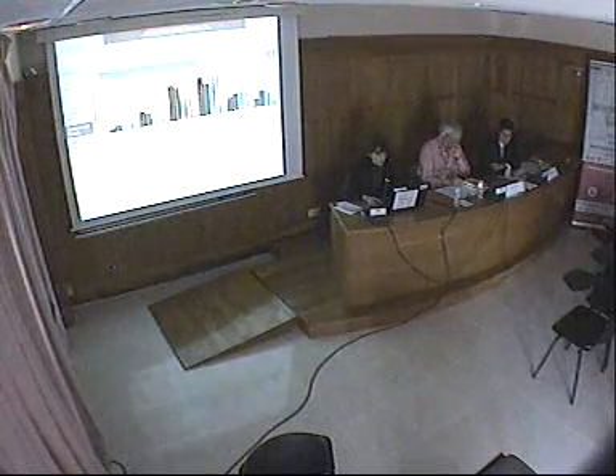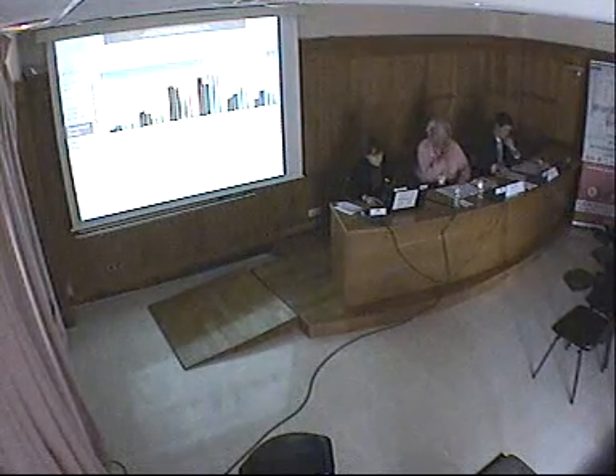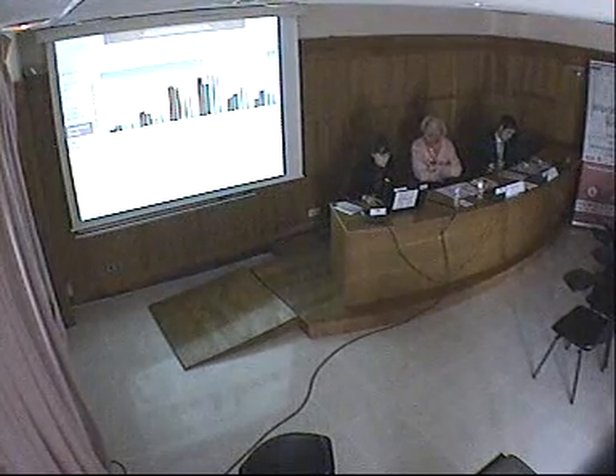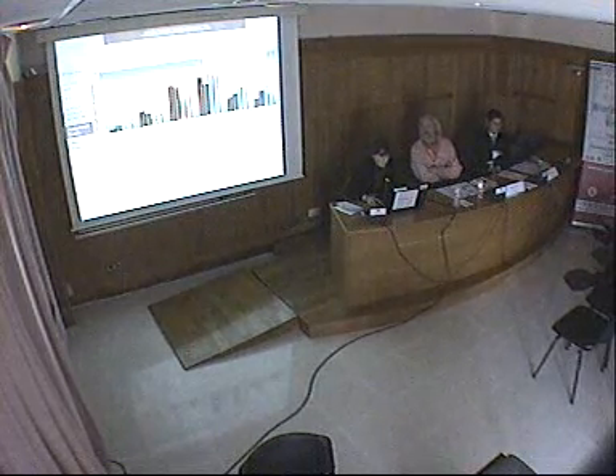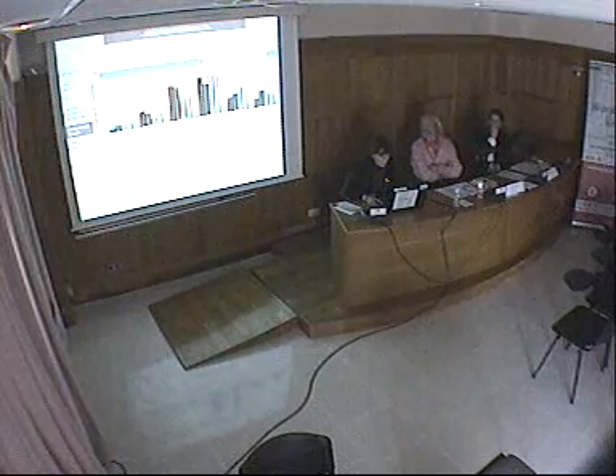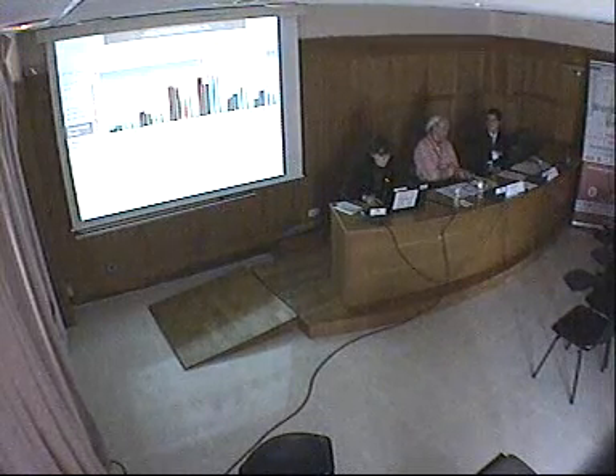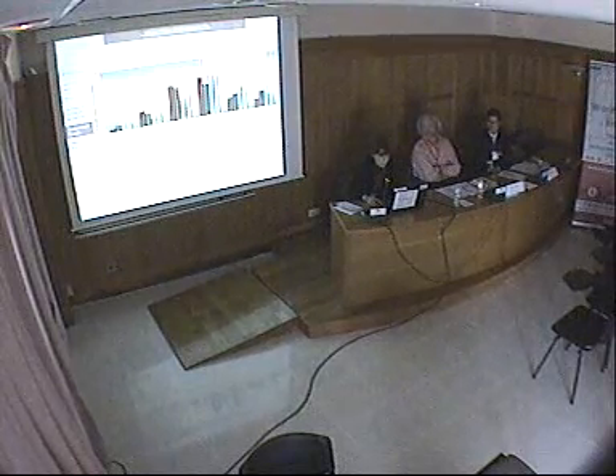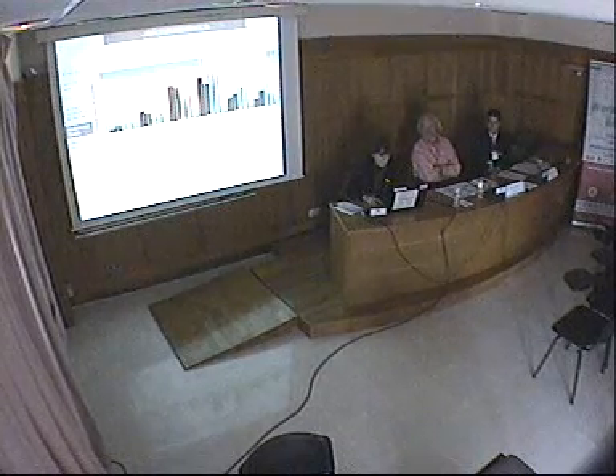Another consideration is about the indoor comfort conditions, and about this we have taken into account the daily frequency of relative humidity value on the inner north surface. In the red box, you can see that the unbaked earth can allow us to achieve a relative humidity value between 60 and 70% for about 14 hours a day. And the best remark that we can make is that the relative humidity goes over 70% for on average 2 hours a day.